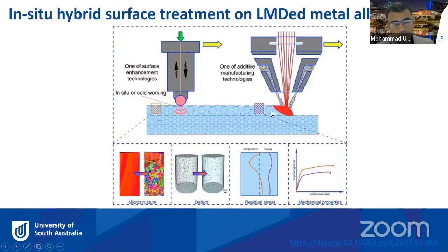the microstructure grain is generally coarse. However, if you add another kind of treatment tool just next to the machine onto the laser head, then you can modify the interlayer just next to the laser deposition here. So by doing the in situ treatment, the cold working, you can modify the surface layer, each layer, in a way to improve the properties as well. So this is one of the results, as you can see.